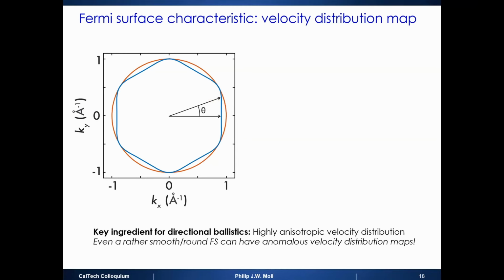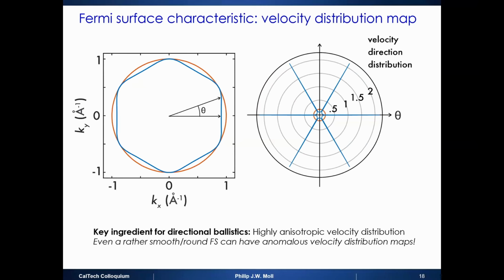You would say it's pretty circular, so there's not a big difference. But of course, the main difference is that the hexagon has all of these facets. The group velocities are, of course, normal to these facets. So here there will be essentially electrons moving this direction, moving that direction, moving this direction, whereas on the circle, they go in any direction. So if you plot a histogram of all of the available velocities, like the group velocity directions, you will find that these things are very different. The circle has completely uniform distribution of velocities, but the hexagon has these spikes for these three directions, with time reversal symmetry, six, that the electrons can move.